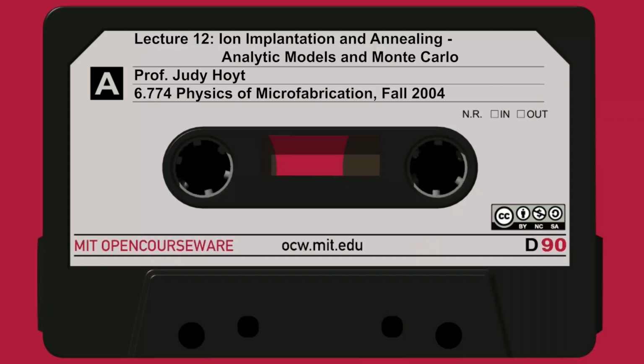Actually, on page 28, here's another example, just as we just saw, of boron. Boron's a famous ion for doing a lot of channeling. It tends to be steered very easily. One problem with ion channeling is that the profile shapes don't scale with dose. Because again, a low dose doesn't damage the profile much. A high dose, here like 2E15, does a lot of damage.